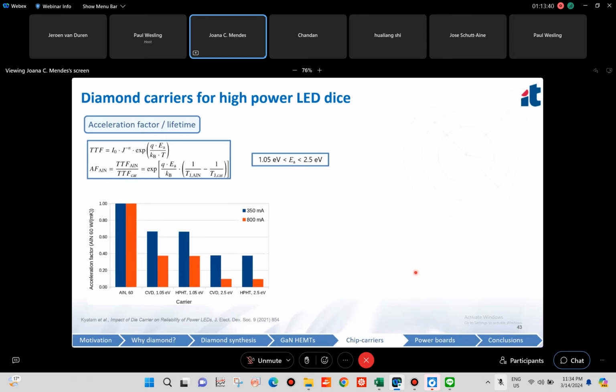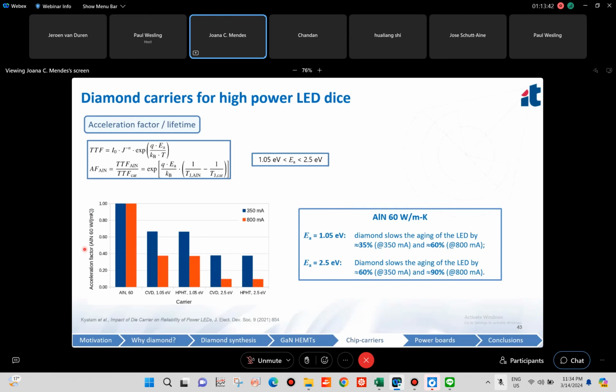And so, depending on the activation energy, whether it is 1.05 or 2.5, we could see that we can estimate that diamond will slow the aging of the LEDs by between 10% and 25% for nominal current. And if they are operated at 800 milliamps, the lifetime increase is between 30% and 50%. Of course, these values are even higher if we have the 60 watt per meter Kelvin aluminum nitride carrier, where the aging is slowed by between 35 and 60% at 350 milliamps, and between 60 and 90% for 800 milliamps current level.